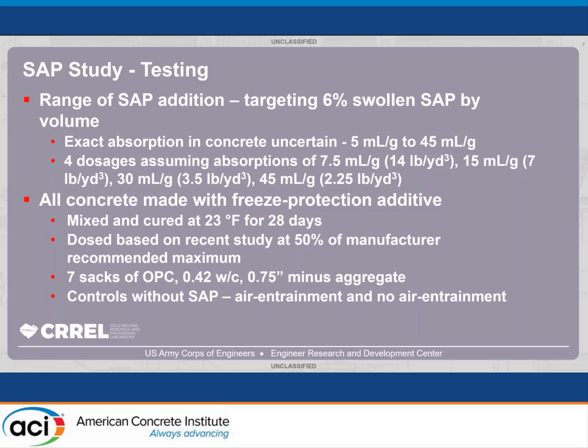And as I said, we're combining this with those freeze protection additives. So we're mixing and curing this concrete at 23 degrees Fahrenheit, and it stayed in that cold space for 28 days.